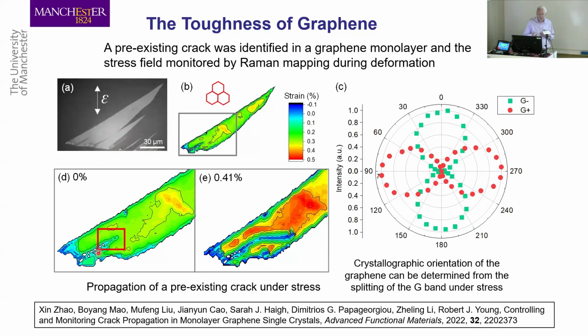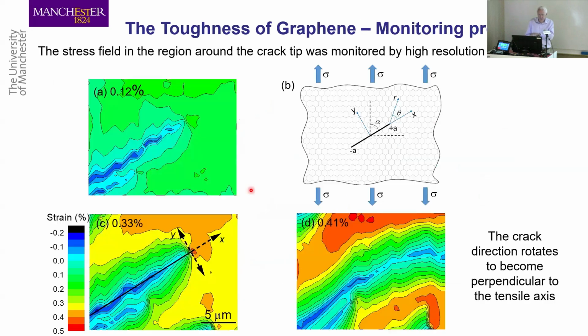We then deformed it, and we mapped out hundreds of data points around the crack and around the crack region. And this is before deformation, and this is after deformation. And you can see before deformation, there's a crack there. Then after deformation, the crack's grown, turned direction, and it was deformed in the vertical direction. So the crack has become 90 degrees to the stressing axis, which is what you might expect. But this is the before and after experiment. I can show you what happened in the meantime. We got quite a lot of interesting information out of it.